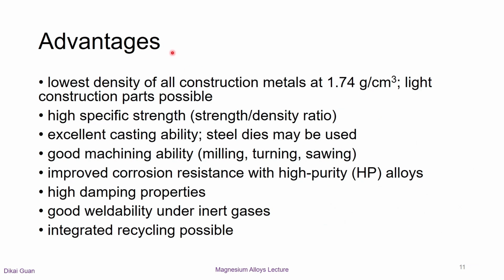Compared to other alloys, magnesium has the following advantages. It has the lowest density of all construction metals at 1.74 grams per cubic centimeter. High specific strength, which is the ratio of strength over density. It also has excellent casting ability, and steel molds are normally used. It has very good machining ability. Sometimes lubricant oil is not necessary. Due to the porous magnesium oxide film, corrosion resistance is not good, but it can be largely improved with high purity alloys.